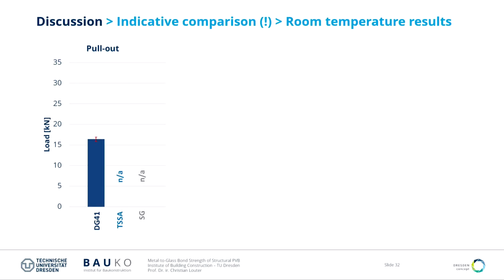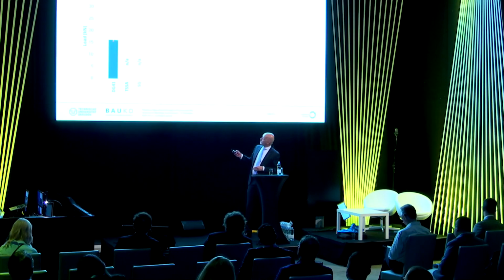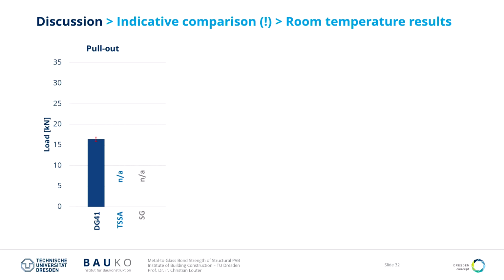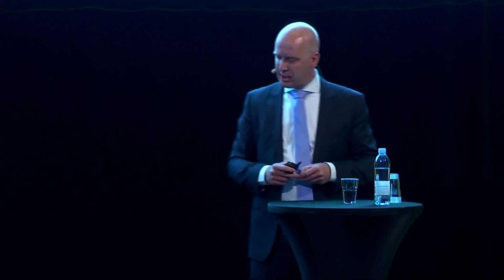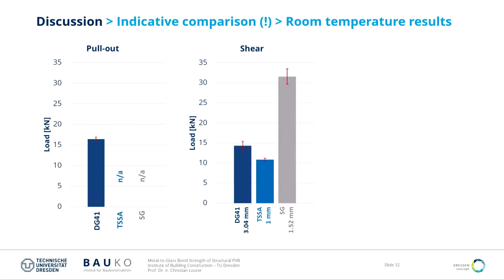Just to give you a discussion, it's of course difficult to relate if I say 14 kilonewton or 50 kilonewton, what that actually is. So I would like to give you a short indicative comparison with other products on the market. This is the result that we got from the pullout test for the DG41, about 16 kilonewton, quite consistent results, very small scatter there. Unfortunately, we didn't do tests on other materials, so we cannot compare it, but for the shear test we could compare it. So we see for the structural PVB quite high shear resistance there, relatively acceptable scatter, small scatter.